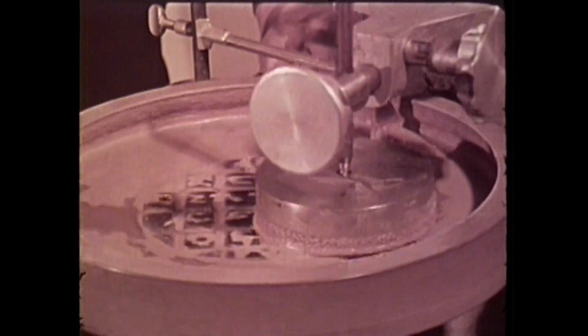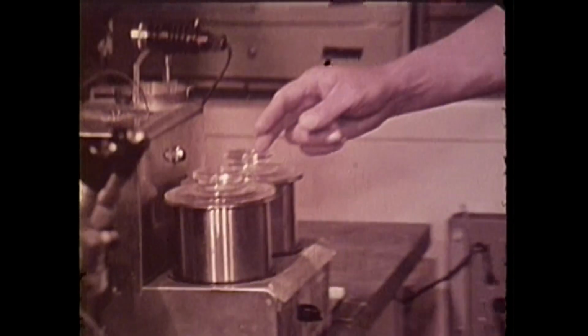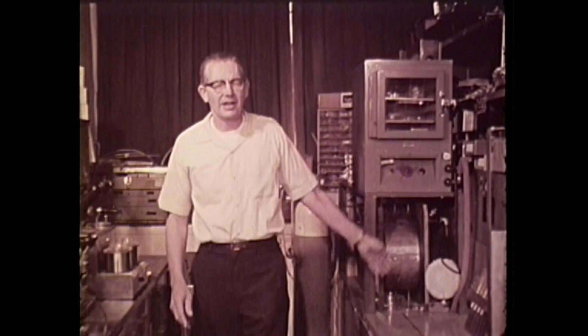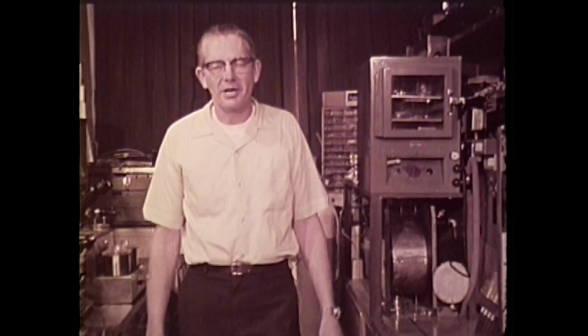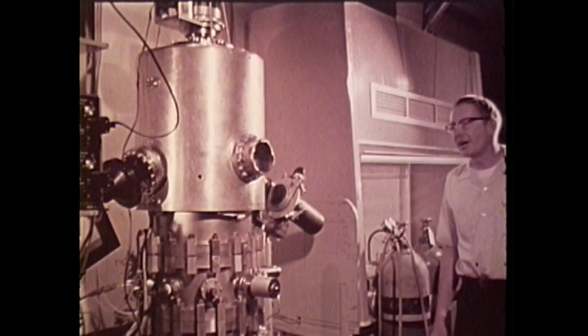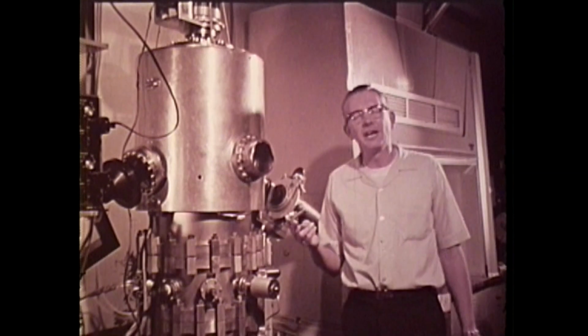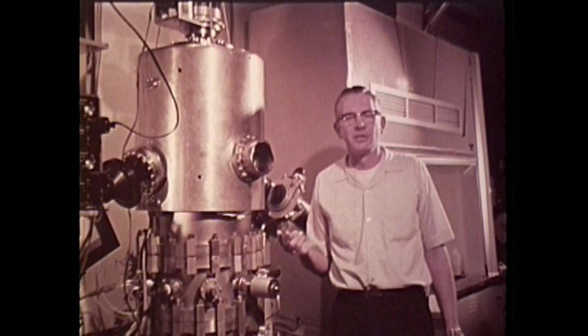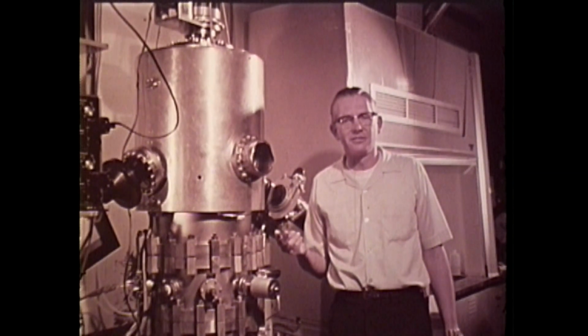In addition to surface smoothness, we've also learned that surface preparation is extremely important. We use a system of ultrasonic cleaning, vacuum drying, and vacuum baking. We deposit the reflecting film in an ultra-high vacuum system held at 10 to the minus 9th torr during the deposition to control residual gases.